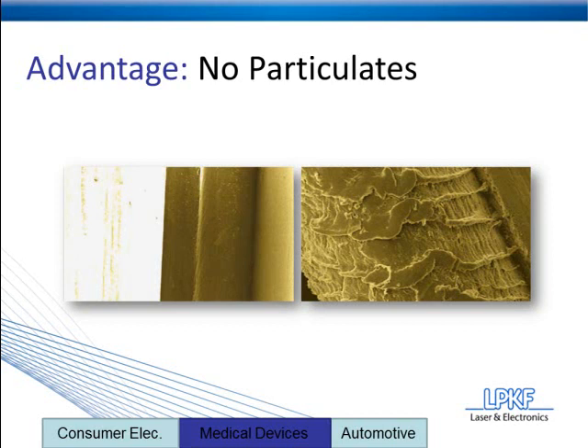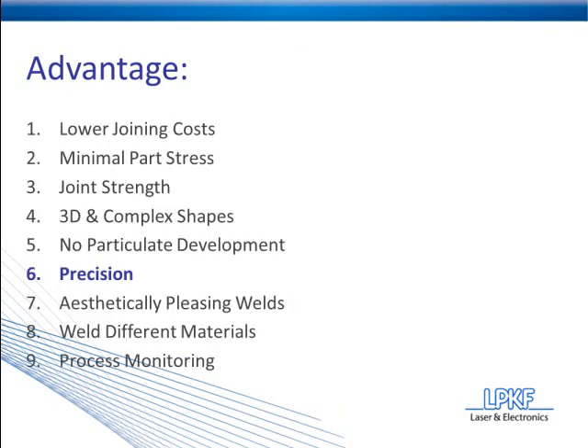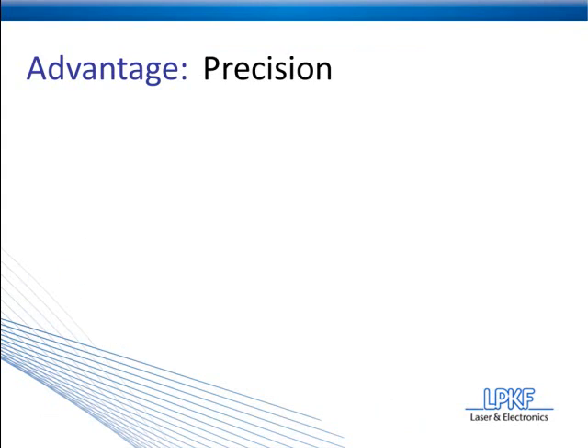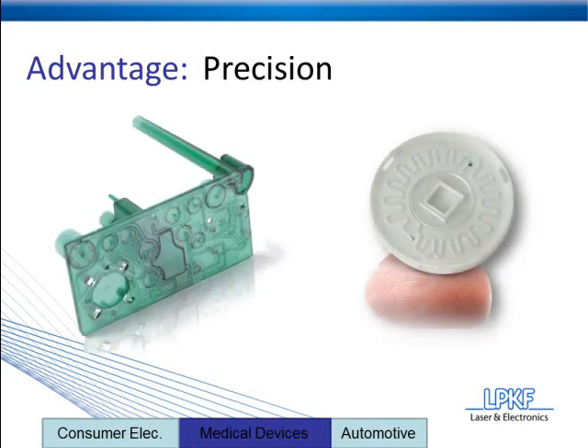So let's move on to advantage number 6, which is precision. Now, laser plastic welding has the ability to create welds in the less than millimeter range. Now, what this means is that devices such as these below were basically made possible by laser plastic welding. So the device on the left is a microfluidic device. Something to take note of with this device is that it's no larger than your cell phone, about 3.5 inches long by 2 inches wide, and there are 2 full meters or 6.5 feet of weld seams within that very small device.